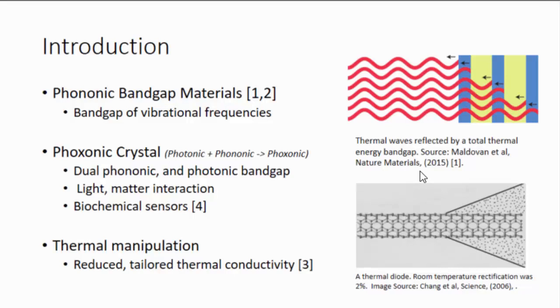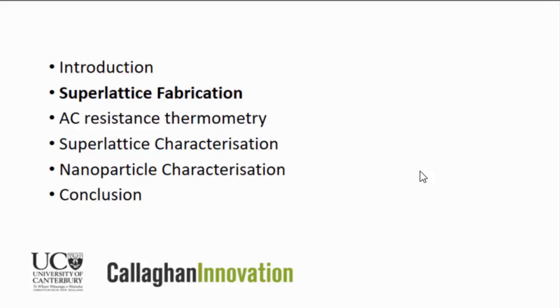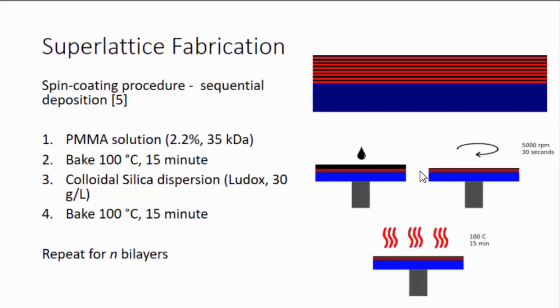So first I'll talk to you about the superlattice structure that I made and how it was fabricated. Like we just saw, this kind of superlattice structure is a variation in material, so it's a stack of different thin films on top of each other. In a photonic crystal, you're varying the refractive index by layer, and in a phononic crystal, you vary the acoustic properties, namely the speed of sound and the density of the material. Both PMMA and silicon dioxide have a large difference in their acoustic properties, and so you get reflection off the interfaces.